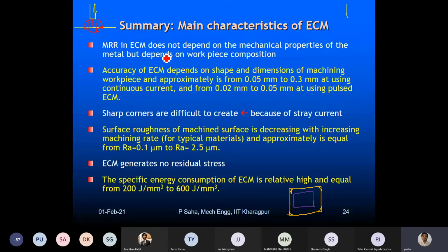The surface roughness of the machined surface in ECM decreases with increasing machining rate, and is approximately 0.1 micron to 2.5 micron. Most important, in the ECM process there is no physical contact, and since there is no thermal issue, there is no mechanical stress and no induced thermal stress. Conventionally that may lead to some residual stress. Even in EDM there is a resolidification process, a recast layer, that may lead to some thermal stress, but here it is completely free from any residual stress.